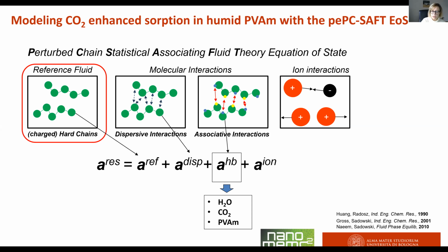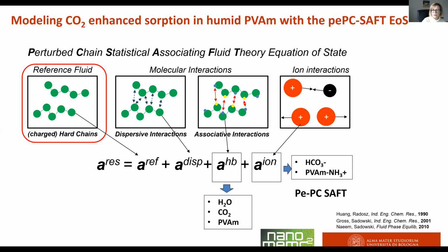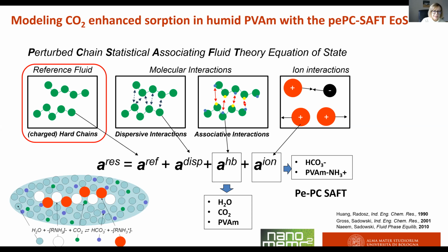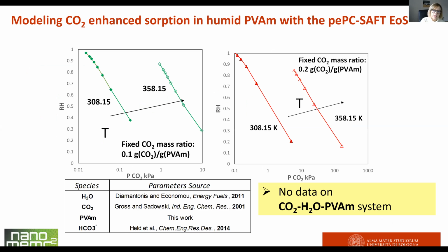The hydrogen bonding term, of course, is related to the presence of associating species, self or induced associating species such as water, CO2, and the polymer, and the ion term is associated to the presence of the diffusing ion and of the ions attached, the aminic ones attached on the polymer backbone. So this is the scheme of the reaction that takes place in the polymer, and these are some results.